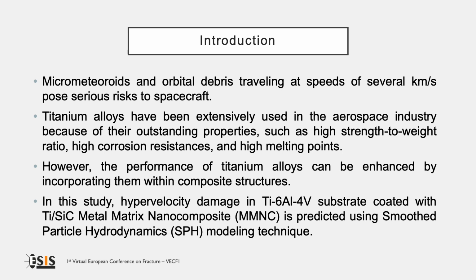Impact resistance can be improved by deposition of a titanium silicon carbide metal matrix nanocomposite coating. For this reason, the aim of this study is to develop a numerical model for predicting failure of the metal matrix nanocomposite coating, using the smoothed particle hydrodynamics technique.